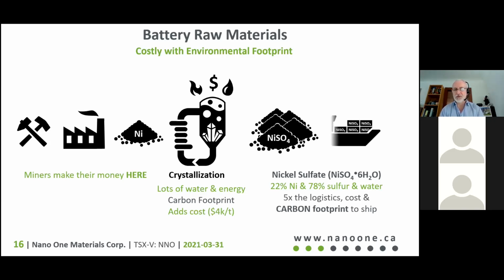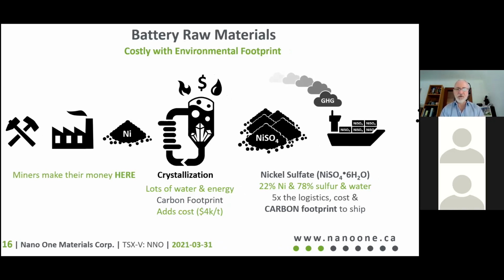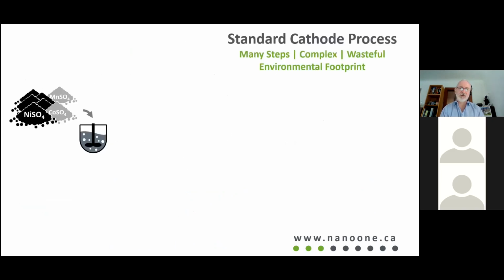When you ship it around the world, you have a lot more greenhouse gas emissions, because for every container of nickel, you have to have 5 containers of nickel sulfate. So the shipping costs go up and the greenhouse gas carbon footprint goes up. When it finally gets to the CAM producer, you add the nickel sulfate, the cobalt sulfate, and the manganese sulfate together in a reactor, and you dissolve it in water. And then you precipitate out what they call a PCAM, a precursor cathode active material.